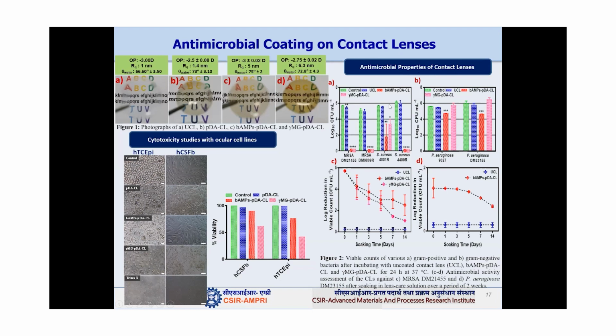Particularly for gram positive bacteria, we are getting 100% eradication of the bacteria from the lens surface if we coat those lenses. Whereas for gram negative bacteria, the reduction is around 90%. 10% of bacteria still survive. So for gram negative, these coatings don't kill 100% of the bacteria, but still the results are very good.